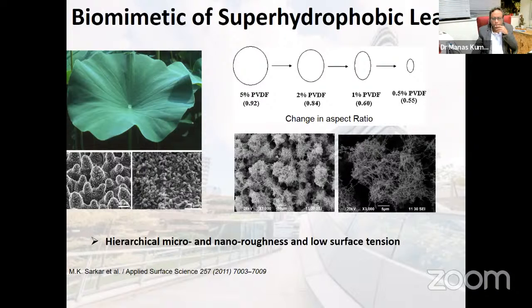So we have observed that the aspect ratio of the particle also has some effect on the super hydrophobic property. When we coat it with 5% PVDF on a fabric using the electrospinning technique, we saw the particle aspect ratio is around 0.92, aspect ratio meaning length to width, so it is more or less the same. When we reduce the percentage of PVDF, the aspect ratio goes lower and lower. That means length is increasing whereas width is reducing. And we observe this has some effect on the super hydrophobic properties.